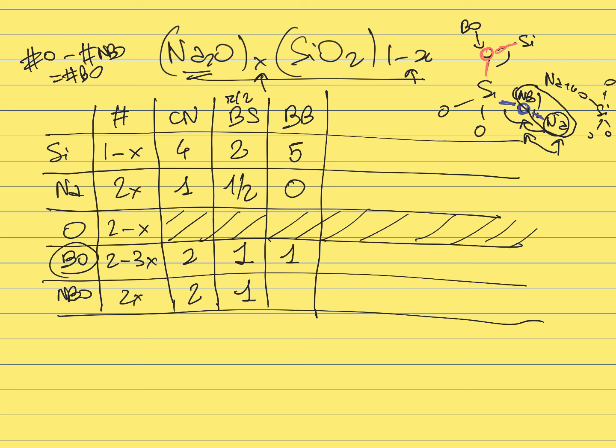There is a great variety in this angle because it's forming an ionic bond between the oxygen and the sodium, and this ionic bond is not directional. The bonds that are directional are the covalent bonds, like silicon-oxygen. This silicon-oxygen angle is going to be directional. It's going to have a fixed value, but the bonds that are forming based on ionic bonds are non-directional. So this silicon-oxygen-sodium angle should not be counted because it's not directional.